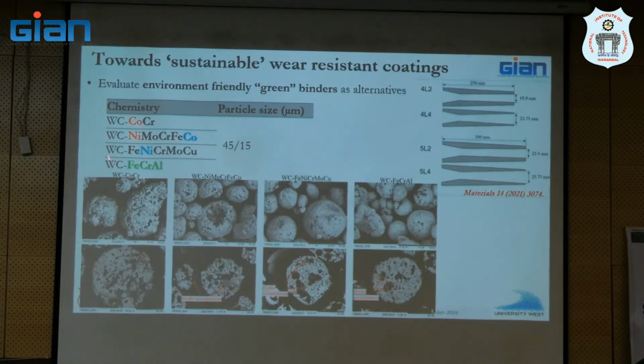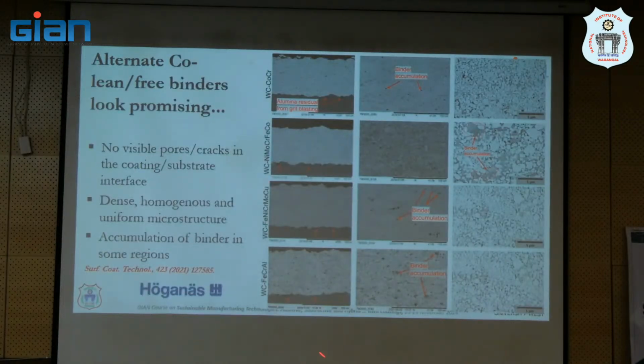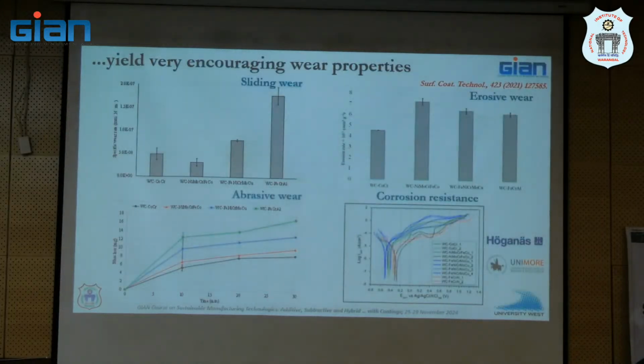For example, we've been looking at what look like complicated chemistries, but they're not actually, right? We work on this with Höganäs, and they have made all these different kinds of formulations for us. The nice thing is, with all of these alternative binders, we get outstanding coatings, right? Same percentage of binder, but the binder chemistry is different. Some of it is completely cobalt free, right? With these two, for example, we get excellent coatings. So that was step one, right? We have investigated it almost to death.